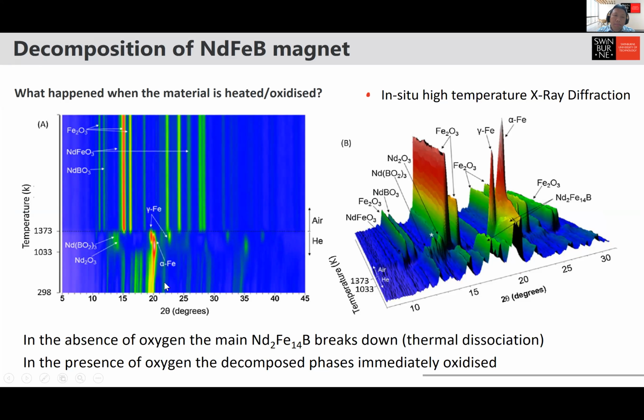So as we heat it up, as you can see in here, you started to produce alpha iron, right? And then Nd2O3 as well as NdBO3, and at higher temperature, we also start to form gamma iron. Now the three-dimensional representation of this can be seen on the right-hand side. So basically, when you heat up the Nd2Fe14B, which is the main phase in the NdFeB magnet, it will thermally dissociate into alpha iron plus Nd2O3 plus a bit of NdBO3.